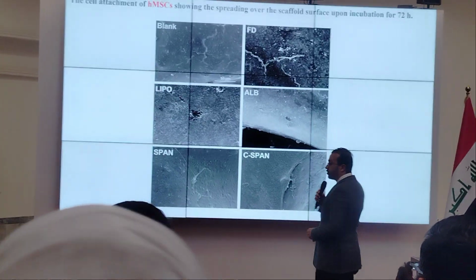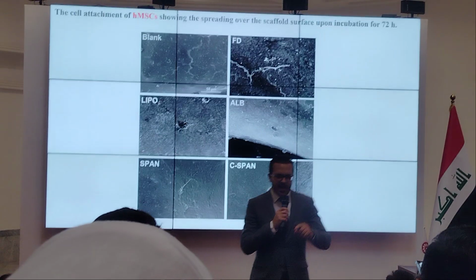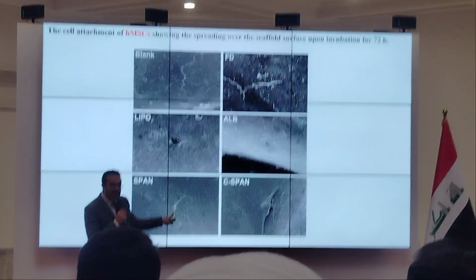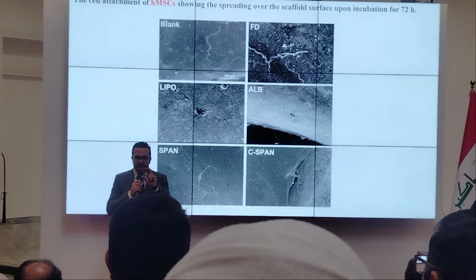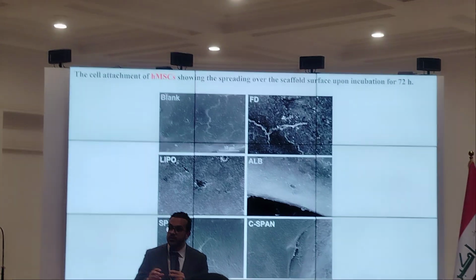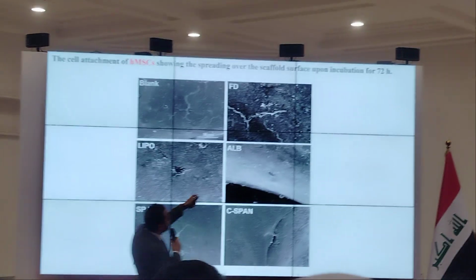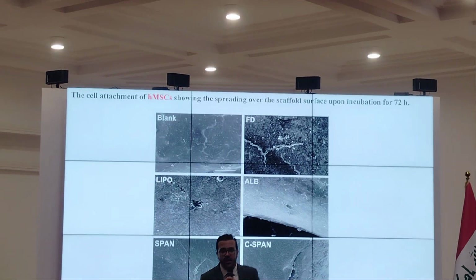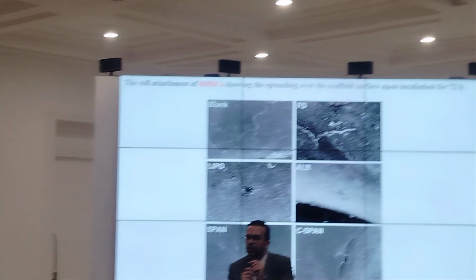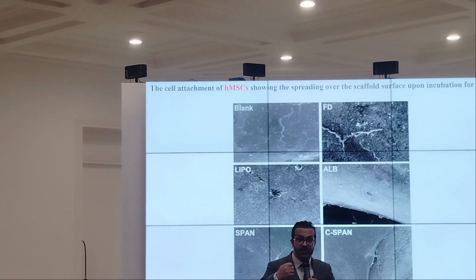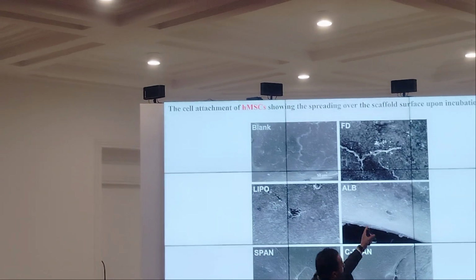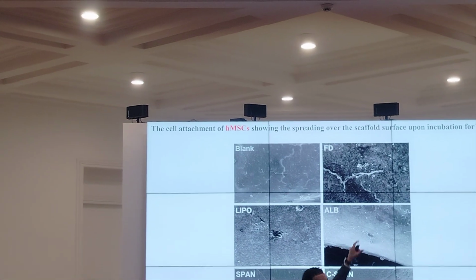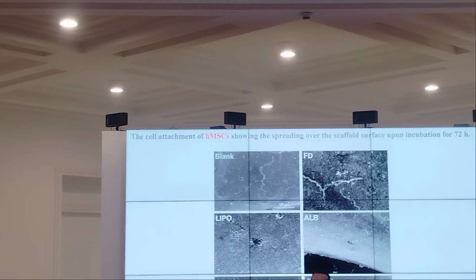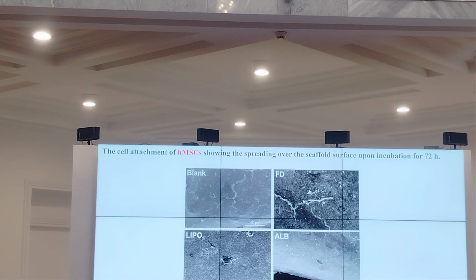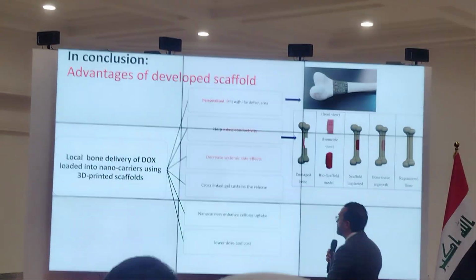As you can see, this was also verified by electron microscopy. And as you can see here, we observed active attachment of the stem cells on the scaffold. Attachment and spreading. This ensures the viability of the stem cells. So the stem cells are viable. Compared to, for example, FD, which is observing the cell attachment after addition of free drug. So with free doxorubicin, in this case, the stem cell is not able to attach and spread, which means that it is dead. As you can see here, it is actively attached and spreading, ensuring the viability and safety of our system regarding the stem cells.